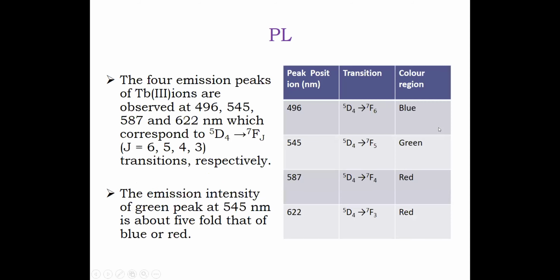Next, please. The emission peak intensity, peak position and also the color region are given in the table. Here the emission peak intensity of the green peak at 545 nanometer is about 5-fold that of blue or red. So the terbium ions are used as green emitters in the doped substances.